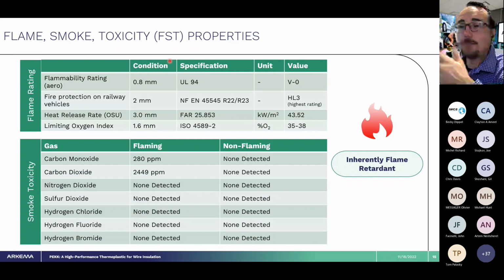I'll only talk briefly on this one. This is a bit of an eye chart, but what I'm showing here is we've done a lot of flame testing on this material. This is an improved material and does exceptionally well. Inherently, there aren't additives put into this material to make it FST. PEKK as a material has these properties on its own. You can see the V0 test, the OSU, low OSU, high oxygen content, oxygen index. And then when you burn it, you get carbon monoxide and carbon dioxide, which is expected based on the chemistry I showed you. So that's fantastic for hazardous applications.